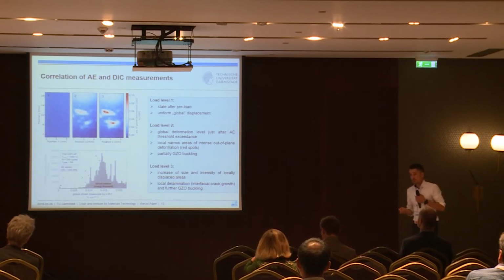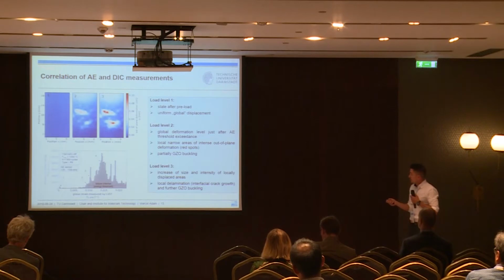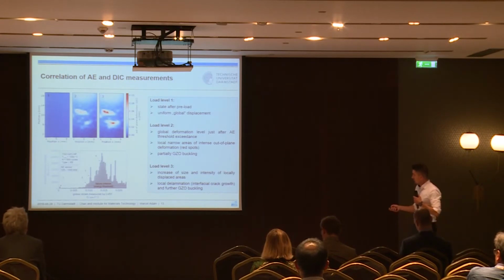From the acoustic emission measurements, we get only the information about when our TBC is going to fail, but we have no information about how it fails. This information we get from the correlation between the acoustic emission and the digital image correlation measurements. So again, here is the acoustic emission energy over the global strain measured for the double layer coating system, which we have seen before. And I marked 4 specific points in the acoustic emission signals. They belong to different load levels.